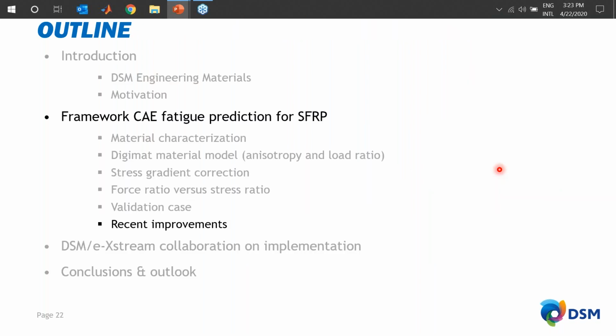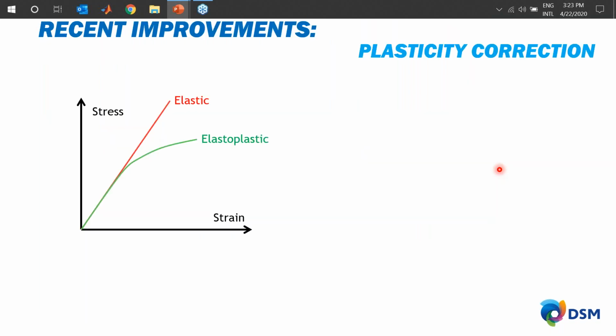Next step would be to discuss some recent improvements. You might already have noticed that I mentioned that we do linear elastic computations. So especially at these high local stresses, you will start overestimating the performance because you will follow this red line, where in reality the material will yield and follow this elastic-plastic performance.